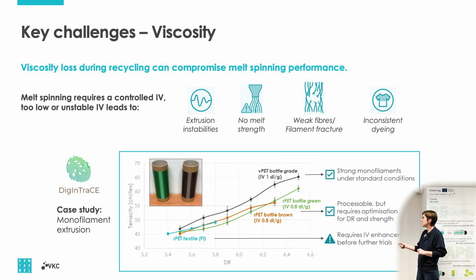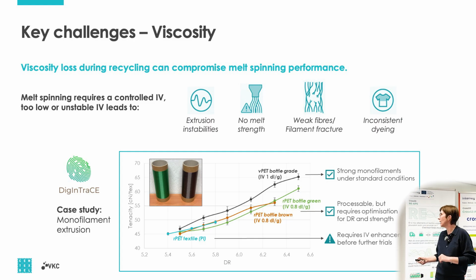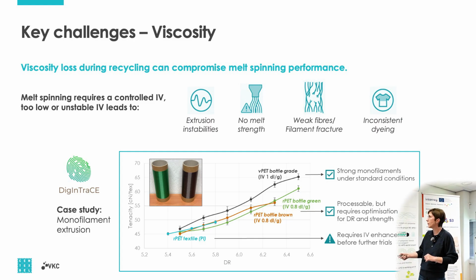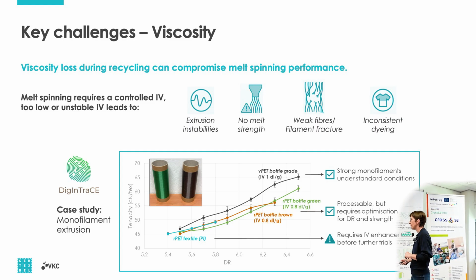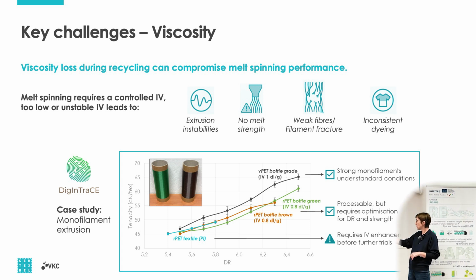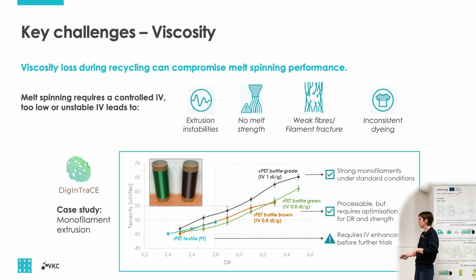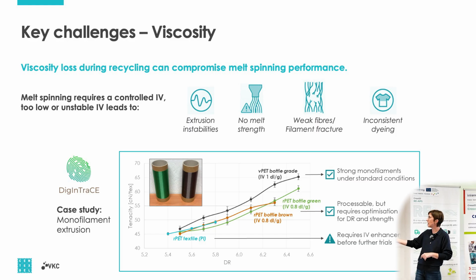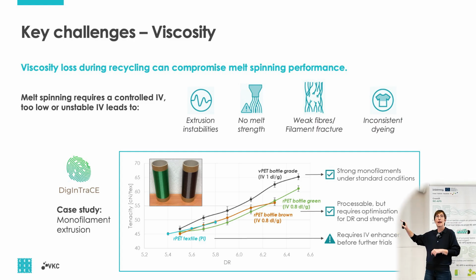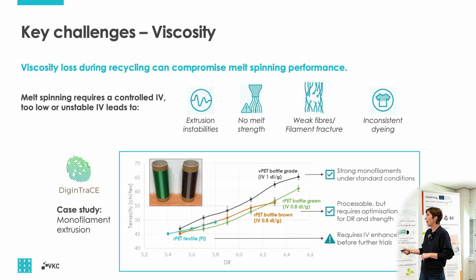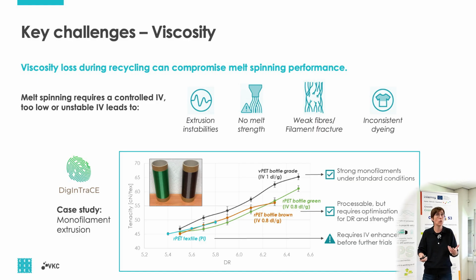Monofilament extrusion, this is a virgin polyester grade, so with a high IV value, an IV value around 1. And you can see with different draw ratios we could really reach high tenacity polyester fibers with a virgin material, standard conditions. If we try to shift to recycled PET bottles, so not yet textile to textile, but if you go from a virgin polyester bottle grade with IV around 1 to a recycled IV of only 0.8, you immediately see the decrease in tenacity we are reaching. So you're really losing, it's processable, but you're losing strength, and you're also reducing your draw ratio. So high tenacity, yeah, but you're already losing some of your properties.